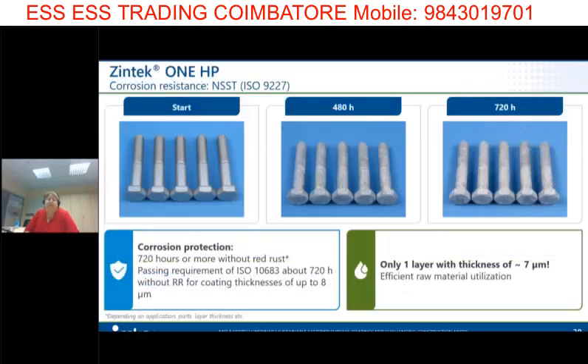Here on the next slide, you see the corrosion results you can really achieve with it. And keep in mind, this is just 1 layer of base coat with roughly 7 micrometers on the screw. And we can achieve 720 hours directly without any red rust. So you can fulfill the corrosion requirement of ISO 10683, which for roughly 8 micrometer systems asks for 720 hours without red corrosion. And we can fulfill this just by having 1 layer. So this is really good.